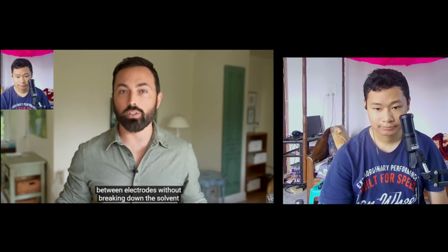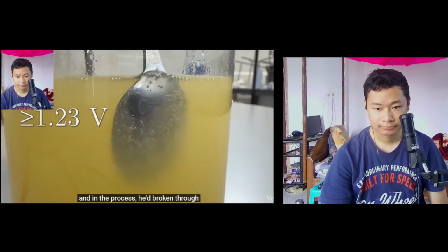It let lithium ions shuttle between electrodes without breaking down the solvent or the cell, at least not until much higher voltages. Whittingham had unlocked lithium's potential, and in the process, he'd broken through the 1.23 volt ceiling. His new chemistry delivered nearly double, a huge 2.4 volts per cell.